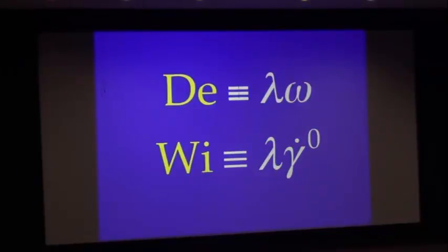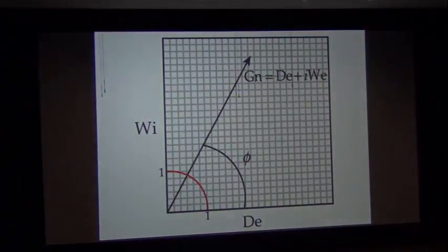We can even map them out onto something called a Pipkin map. Nonlinearity on this axis, elasticity on this axis. That's our old friend Newtonian fluid mechanics near the origin there. And the further I get away from the origin, the more important those higher harmonics will be. So he said we should do this with the co-rotational Maxwell model.